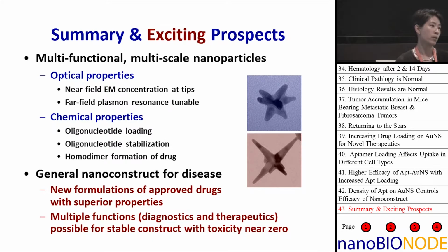And so that's typically how we do the chemistry for that. Because the gold-sulfur bond is pretty stable. It's on the order of 2.5 to 3 electron volts, so it's not going to come off that easily. But when you put it in the biological system, what happens? Right. Okay, these bonds will be cleaved, right? No, the bonds are not cleaved.